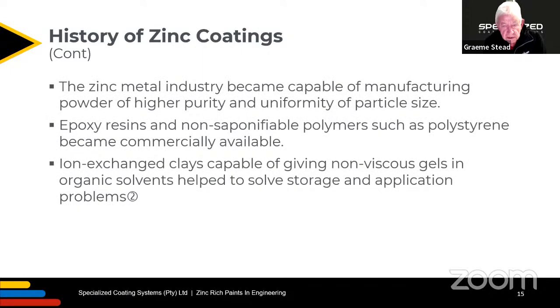The zinc metal industry became capable of manufacturing powder of higher purity and uniformity of particle size. Now that is very important. Epoxy resins and non-saponifiable polymers such as polystyrene became commercially available. And polystyrene has been superseded by very much more stable polymers such as acrylics and vinyls and many other polymers. And then ion exchange clays capable of giving non-viscous gels and organic solvents help to solve storage and application problems.